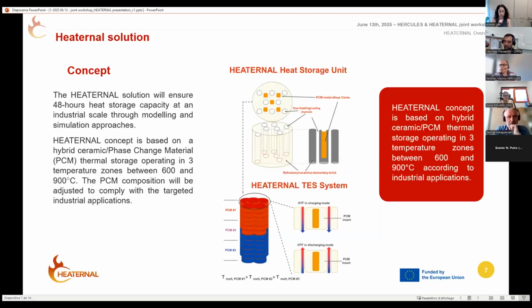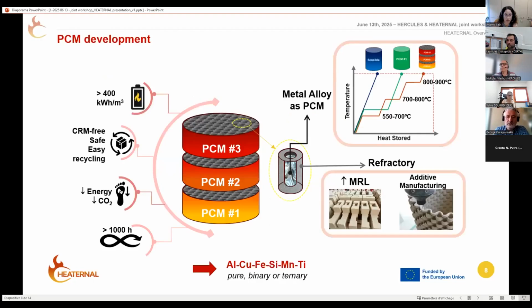So the HEATERNAL concept is based on a hybrid storage using ceramic and phase change materials, so-called PCM. And this hybrid unit is represented on the top picture of this slide. And the lower picture shows that the storage would be able, in fact, to operate in 3 temperature zones, depending on the industrial application, and in the temperature range from 600 to 900 degrees. So each PCM in each zone undergoes a phase change at different temperatures. And thanks to this phase transition, each PCM enables to increase the energy density of the whole thermal storage.